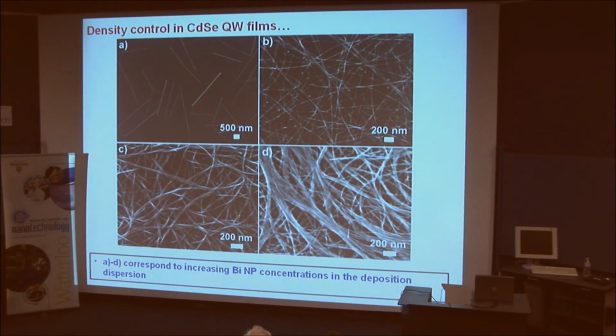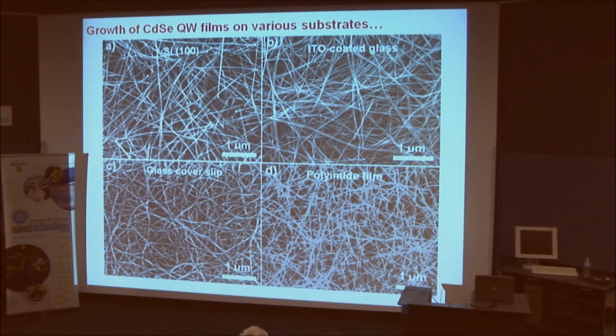So now, how about density control? Well, if we put the bismuth particles on the substrate at a low density, we get this. If we put them on at a somewhat higher density, we get this. These bright spots are actually bismuth particles that are on the ends of the wires. At a higher density, we start to now see some wire bundling, which becomes extreme at even higher densities. So we have some control over the wire density on the substrates.